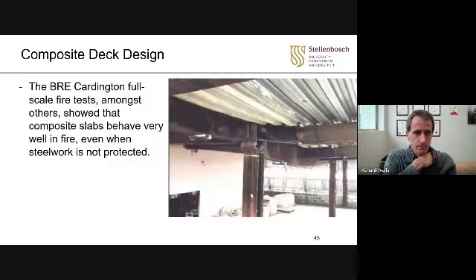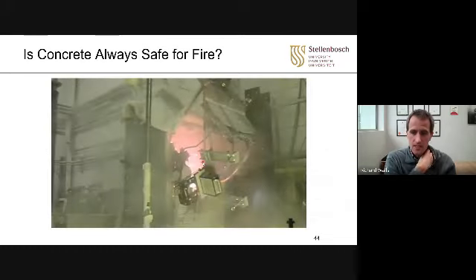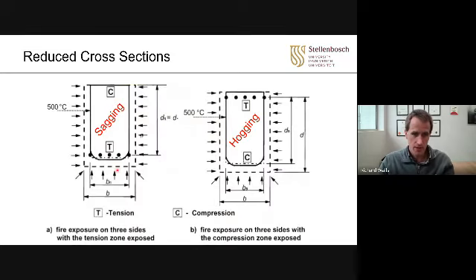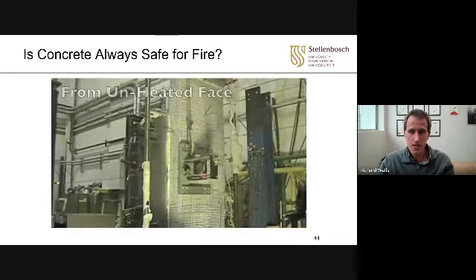And so that is now starting to require different test methodologies, especially in your high-performance concrete. So for instance, for tunnel design, what they actually have is a little mobile furnace that you move in, you put it on the side, and then you run a fire test and you see, would my concrete lining spall? Because you can't use this method if you have spalling, because this method assumes the concrete stays in place. But if you have explosive spalling, it's a big problem.